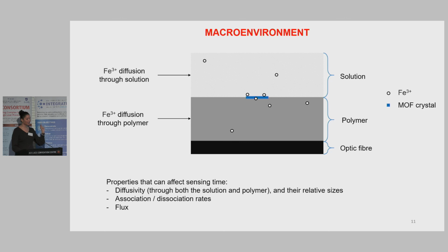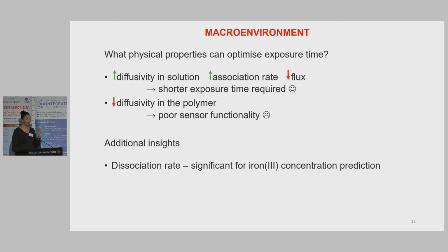So the diffusivity of iron 3 in solution and the polymer, and its relative sizes between the two diffusion constants, the association rate, so how quickly iron 3 binds to the crystal, and dissociation rate, how quickly iron 3 unbinds from the crystal, and then flux of iron 3 at the crystal. From these four properties, we can now answer our question. If we increase diffusivity, association rate, and decrease flux, we have a shorter exposure time.